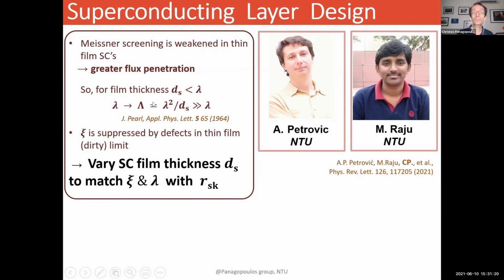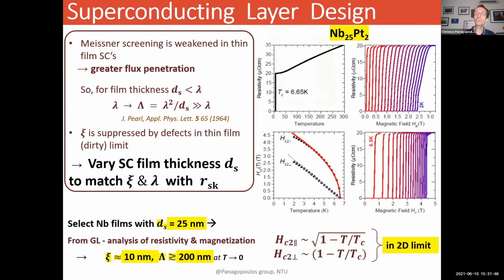And therefore here you would expect that the coherence length, the superconducting coherence length, would be suppressed by defects in the thin film because you are in the dirty limit. So what you need to do then is vary the superconducting film thickness ds in order to match the coherence length and the magnetic penetration depth with the size of your magnetic skyrmion. And with that, after a lot of effort and trial and error, we were able to select niobium films with a thickness of 25 nanometers.